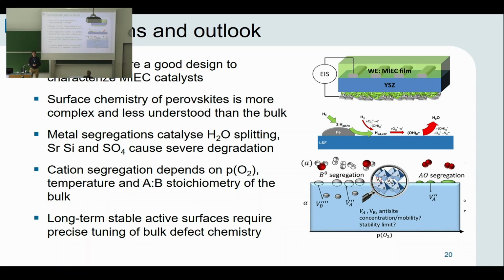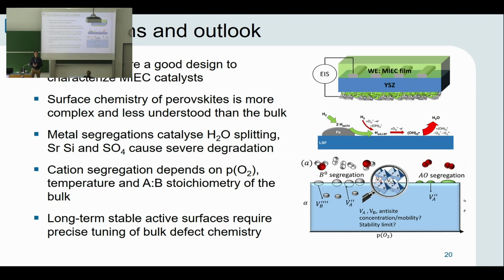Okay, so a quick conclusion on my talk. Model solid oxide cells are a very good design to investigate the kinetics and defect chemistry of our mixed conducting catalysts. However, the surface chemistry, in which we are mostly interested, is very different from the bulk, but still at high temperature, it will equilibrate over some time scale with the bulk defect chemistry. So we need to understand the bulk defect chemistry in order to know at which conditions the surface chemistry is at least stable. Also, we have shown that metal segregations can catalyze reactions, especially water splitting, whereas strontium segregation as well as impurities can really hamper the kinetics.